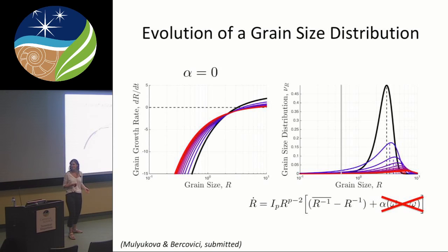Sorry, do I have a minute for a little sidetrack? Jennifer is an experimentalist, and I'm a theoretician, and we sit in the same office. She's working in Shun Karato's lab, doing this deformation of rocks. We've looked at some of her samples together and really tried to get out what the real grain size distribution is. It's been a source of frustration that most deformation studies I've looked at do not report your full grain size evolution. And I understand why. It's difficult to fish it out from just looking at your sample.